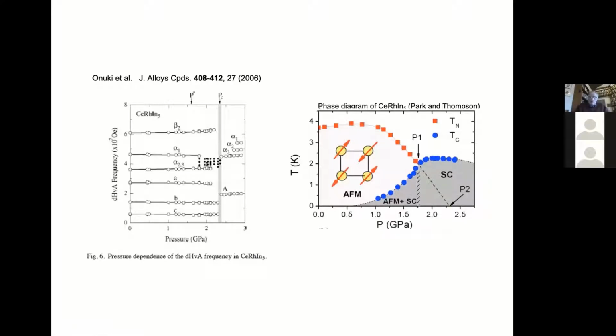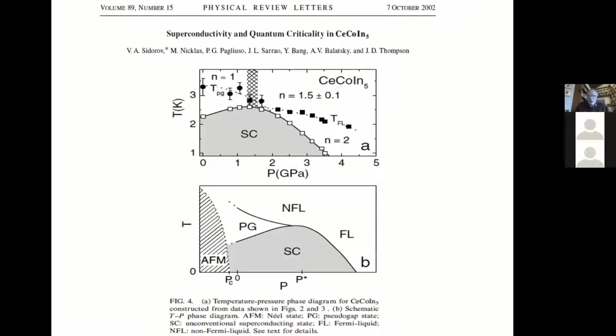A further confirmation of this thinking is that you can make the tetravalent thorium rhodium indium 5 compound in this structure, and it has a Fermi surface quite similar to this high pressure phase. That also supports the thinking that the f electron is included within the Fermi surface. These experiments were done on thorium rhodium indium 5, not so easy to make, by the group in Tokai. So this is the phase diagram with pressure of ambient pressure superconducting cerium cobalt indium 5, the sort of poster child in a certain way of heavy fermion cerium superconductors.